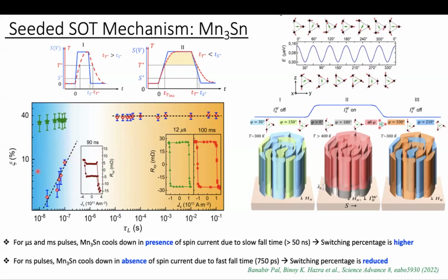In the nanosecond case, one can see the pulse fall time is very fast. It's of the order of 750 picoseconds. In that case, the system relaxes in the absence of spin current, because of this sharp drop and very fast fall time. So that's why the full switching doesn't happen, and we observe only partial switching. That's why the switching percentage is less than 10%. And if you go to even lower pulse width, the switching will be very small.